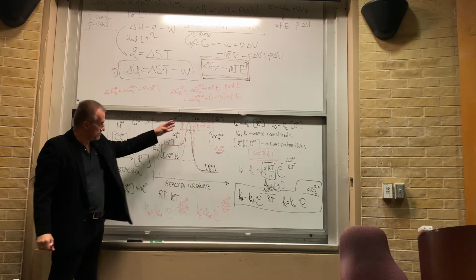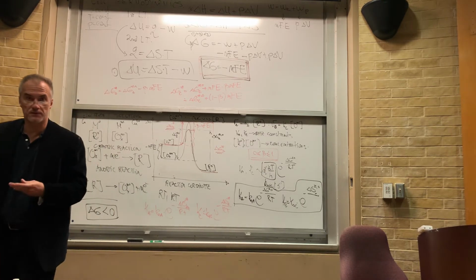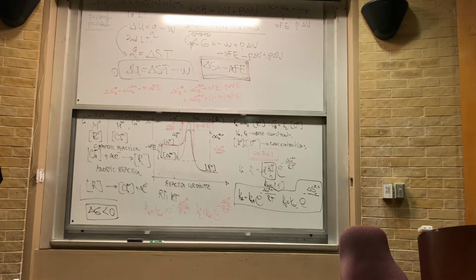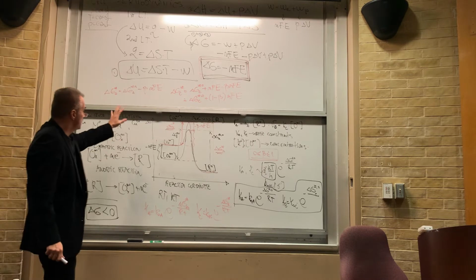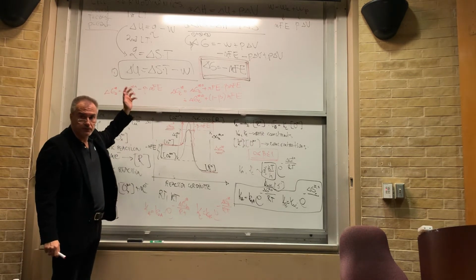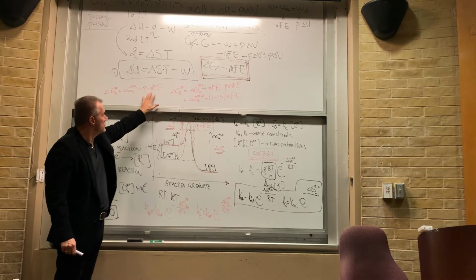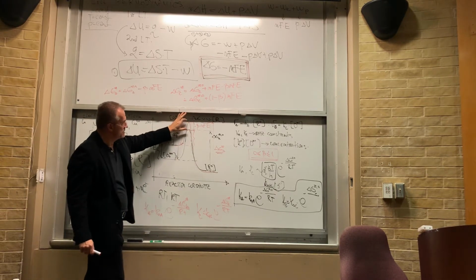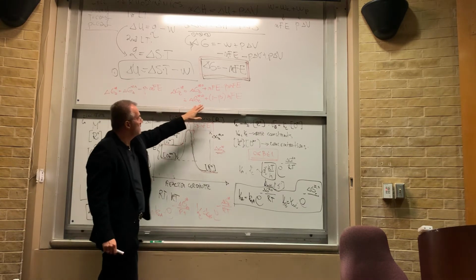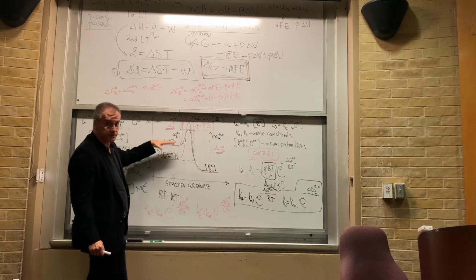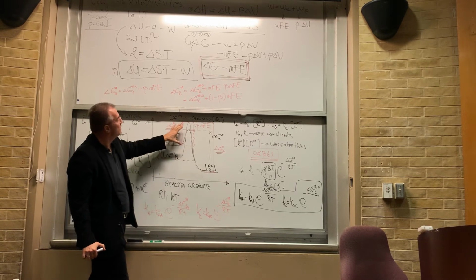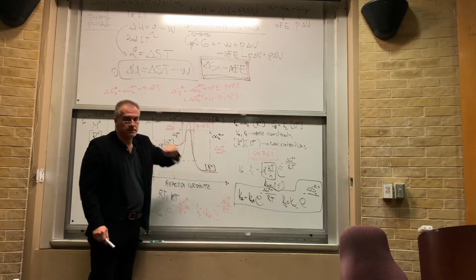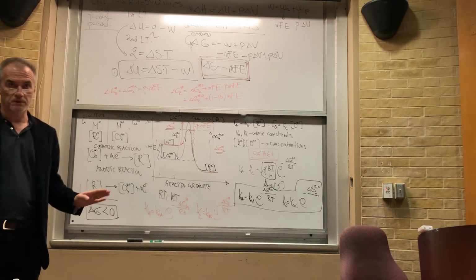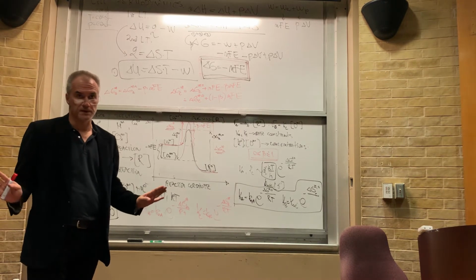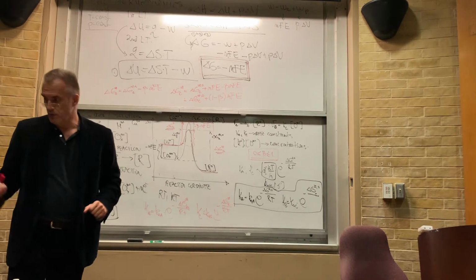So now we have the activation energies when we add the field across the interface, which basically brings in our whole discussion of electrochemical reactions, right? From chemical to electrochemical, basically as you can see, the activation energy is just modified for the anodic process due to this term here, which increases a little bit the activation barrier. And here it is a little bit more complicated because we are shifting the energy state of the product or the reaction, and then we have to do a little bit more math, but it's relatively simple. Are we clear with this? Because if you're clear with this, then you have no problem with anything else besides math. Okay?